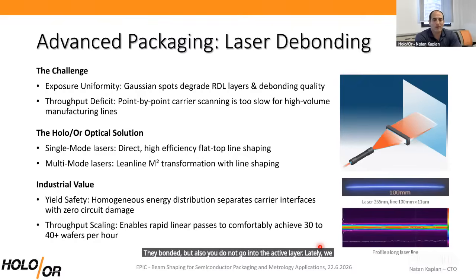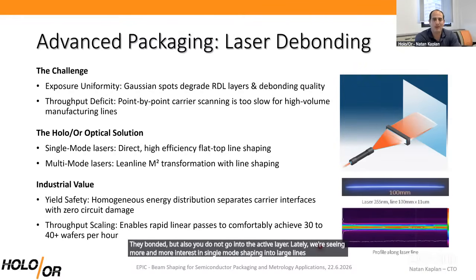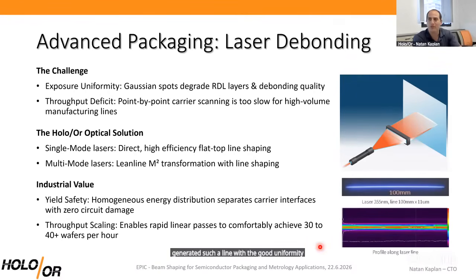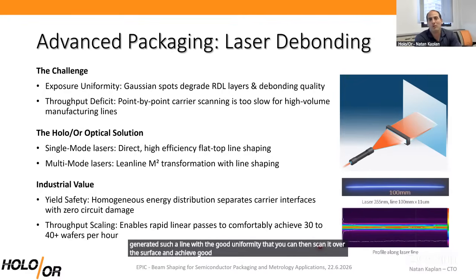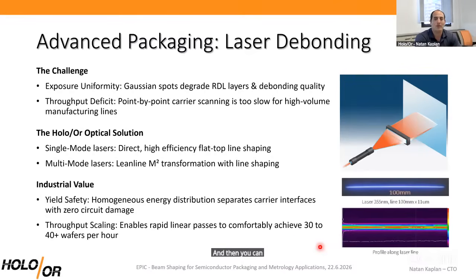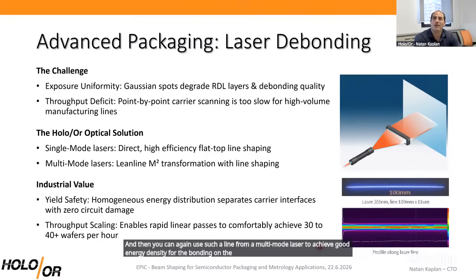Lately, we're seeing more and more interest in single mode shaping into large lines, even 100 millimeter, because single mode laser power is becoming more and more available for such applications. And there, again, we have shapers. Typically, they are refractive shapers, but again, single element shapers that can generate such a line with a good uniformity that you can then scan over the surface and achieve good debonding. For multi-mode cases, we offer a solution based on M-squared transformation where you rearrange the M-squared so that the beam has a lower M-squared in the line direction, the narrow direction, and a high M-squared in the long direction. Then you can, again, use such a line from a multi-mode laser to achieve good energy density for debonding along the scan and the wafer.